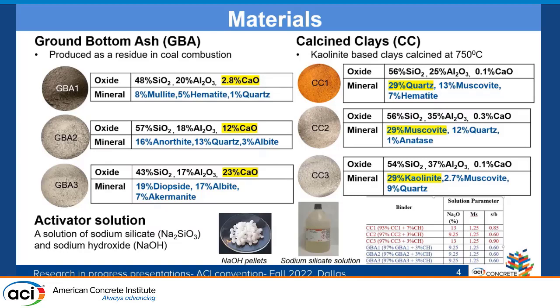The calcined clays used were mainly kaolinite based calcined clays, calcined at 750 degrees Celsius. These three materials also have different oxide and mineral compositions based on the studies we've done. As the activator solution, I used a solution of sodium silicate and sodium hydroxide.